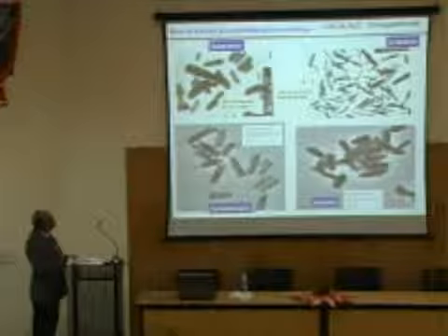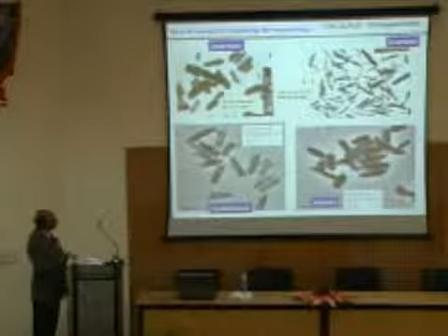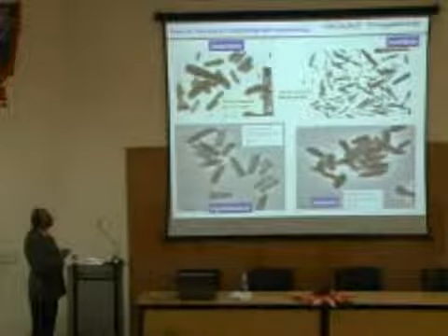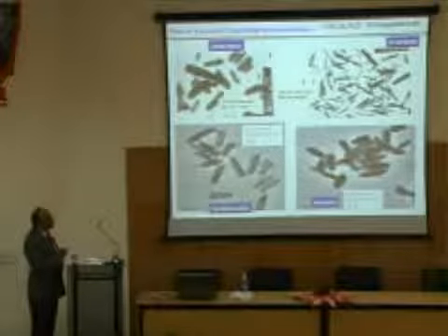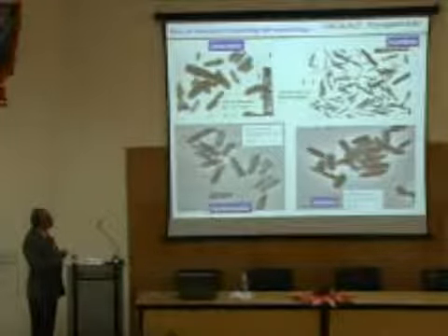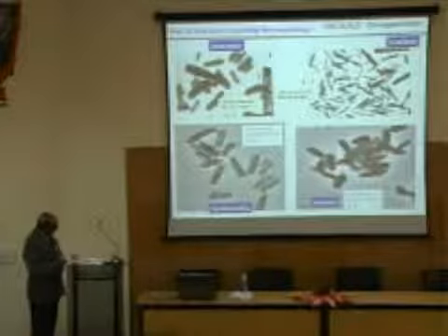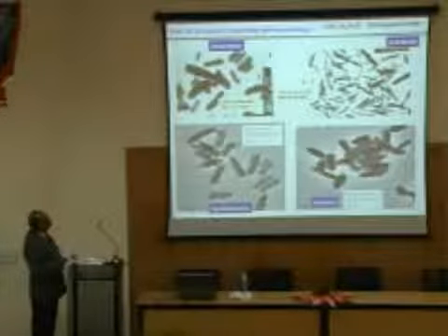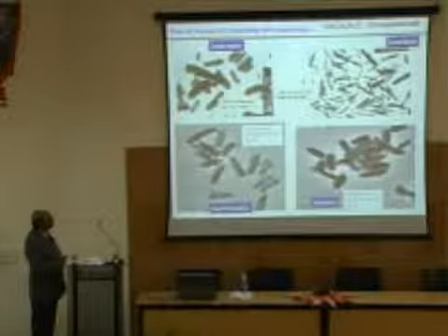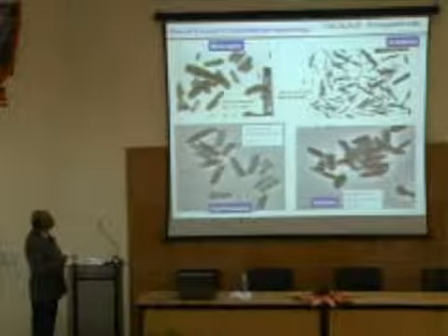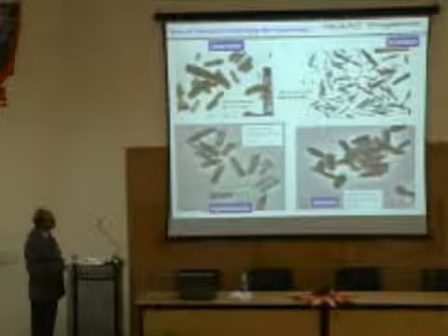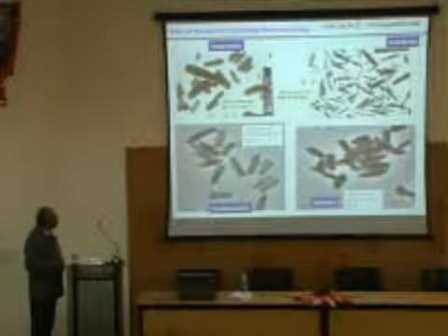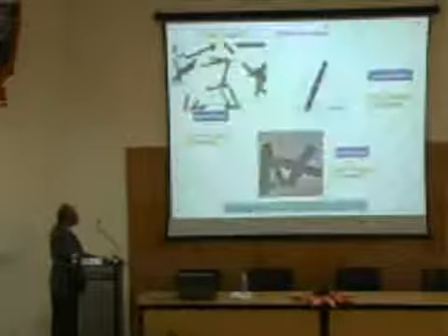Now, one of our aims is to control the aspect ratio of the rods, because you need to control the length and the width of the rods. So if you want to make rods or wires, you have to control them. And we have done a detailed investigation of how you can control this aspect ratio by varying the kind of solvent. This is to show if you change the solvent from isooctane to normal octane, etc., you can change the aspect ratio from 4:1 to 6:1. So you can modify the aspect ratio of these rods.